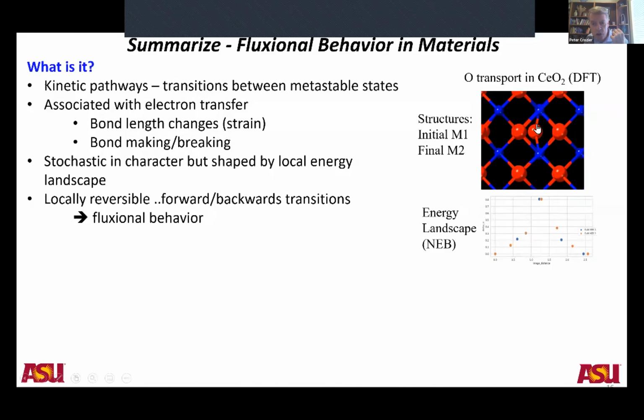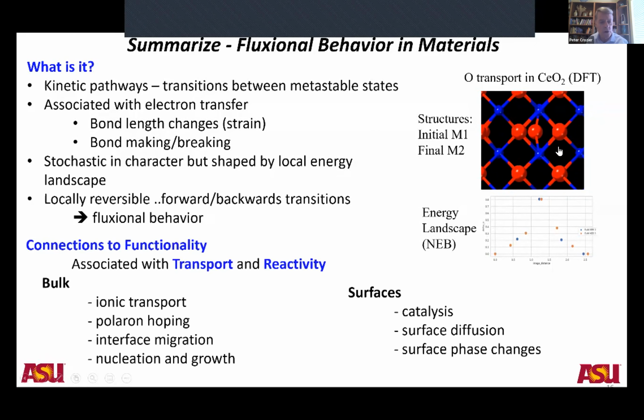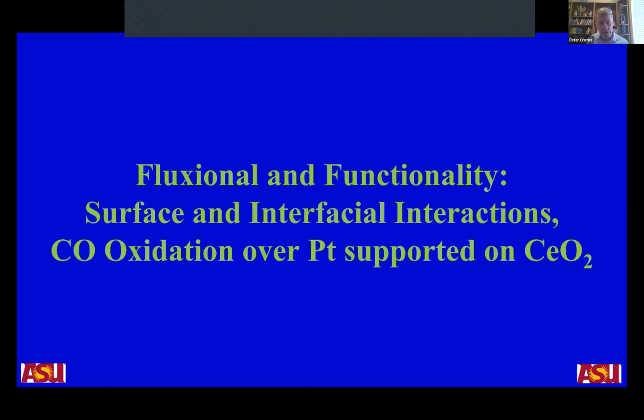And if you look at the local strain field associated with M1 and M2, they're different. So in principle, you would be able to differentiate the oxygen in those two different sites by characterizing the strain of the initial and final metastable states. So even though we're using it mostly for catalysis, of course, it would apply to transport. So for example, bulk transport, ionic transport, what I'm showing you with the DFT simulations, things like polaron hopping, interface migration, nucleation and growth, and then of course on surfaces, things like catalysis, surface diffusion and surface phase changes. So this is what we're calling fluxionality. And we think that in the electron microscope, we can actually measure this.